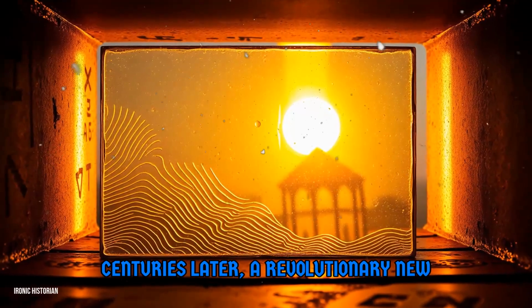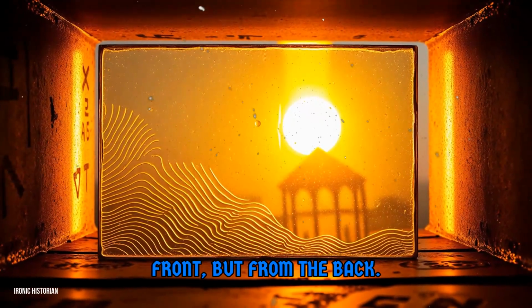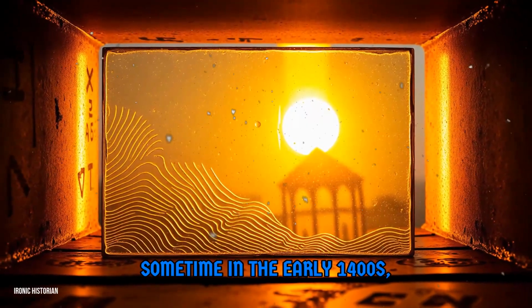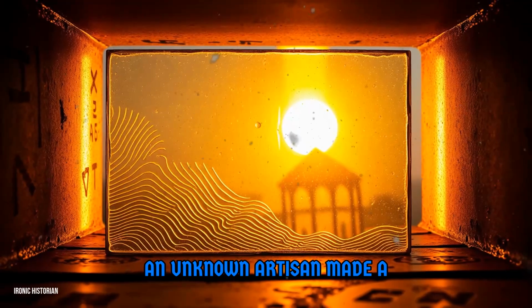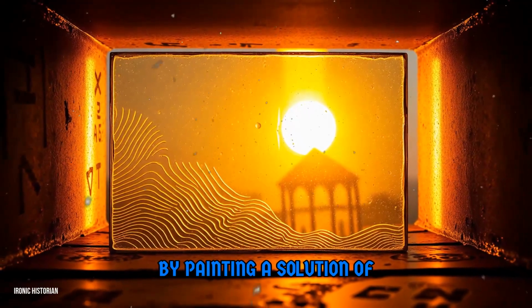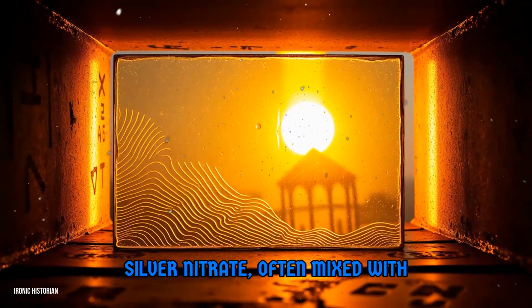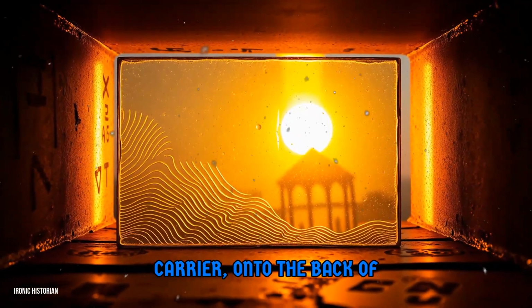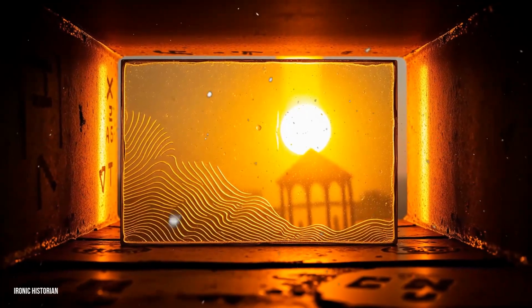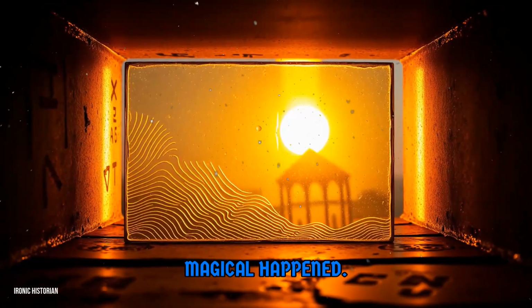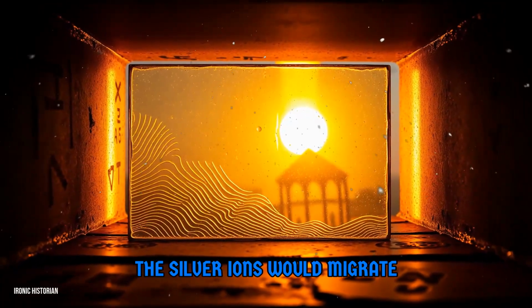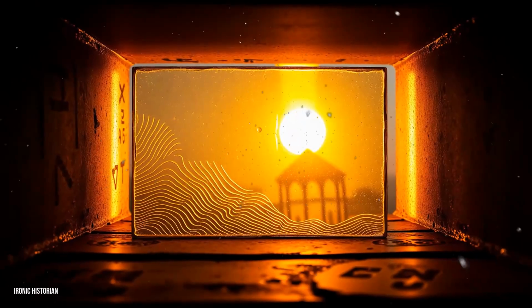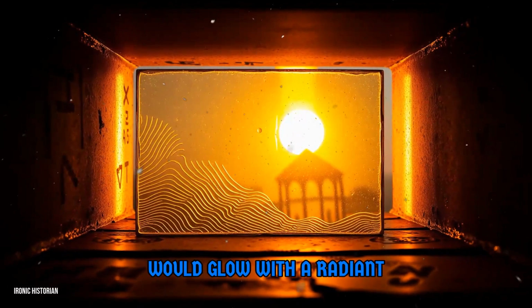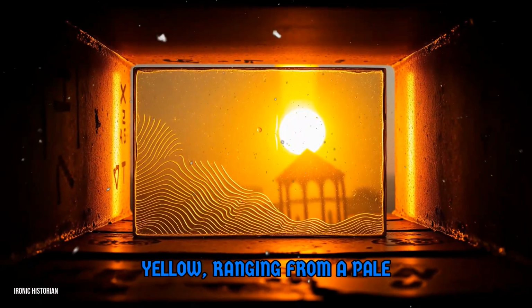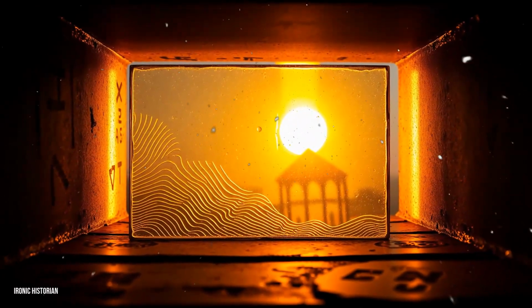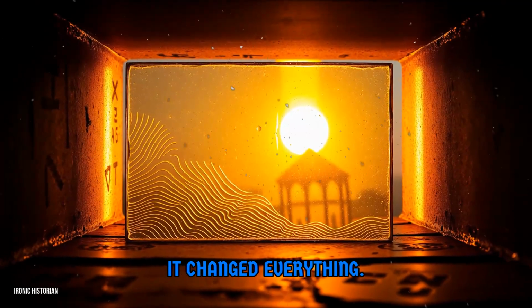Centuries later, a revolutionary new color arrived, not from the front, but from the back. Sometime in the early 1400s, an unknown artisan made a stunning discovery. By painting a solution of silver nitrate, often mixed with yellow ochre clay as a carrier, onto the back of a piece of clear glass and then firing it, something magical happened. The silver ions would migrate into the glass surface during firing, and when cooled, the pane would glow with a radiant yellow, ranging from a pale lemon to a deep, honeyed orange. This was silver stain, and it changed everything.